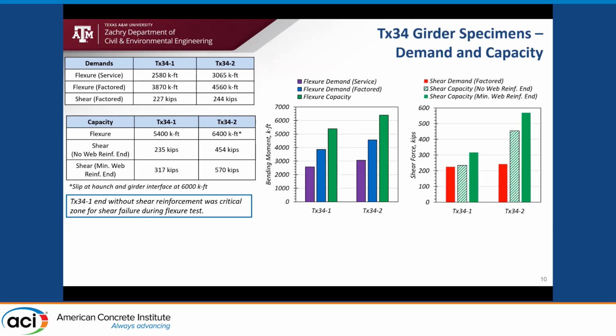As I mentioned earlier, the first specimen had slightly lower tensile strength and all straight strands with lower pre-stressing, and that can be reflected in the performance of the no web reinforced end being ever so slightly higher than the factored shear demand. However, the transverse bars provide better resistance in this specimen. For the second specimen with higher tensile strength, more pre-stressing and harped tendons, we have more contribution to shear, and that is easily reflected from the better shear performance of both the ends when compared to the factored demands.